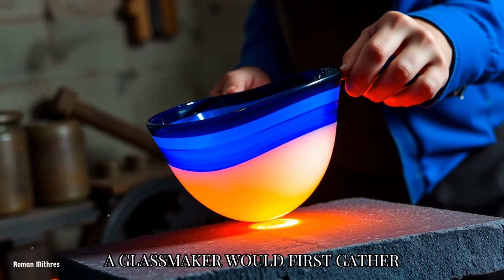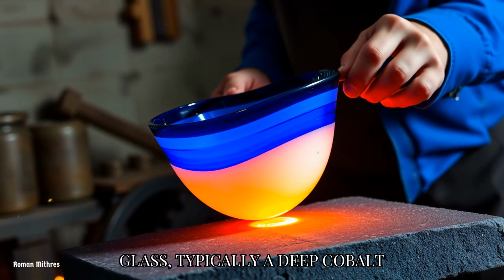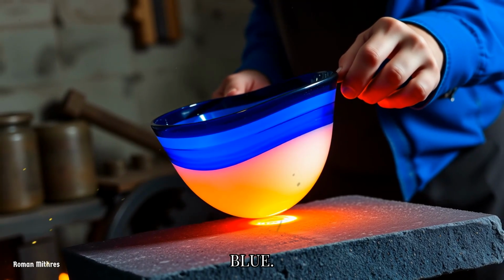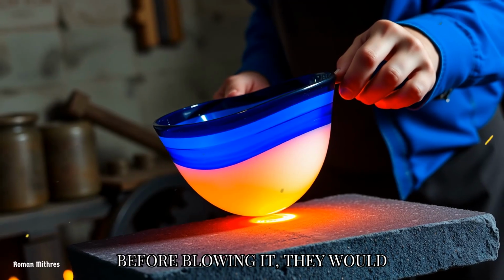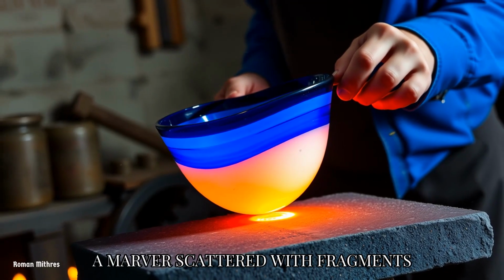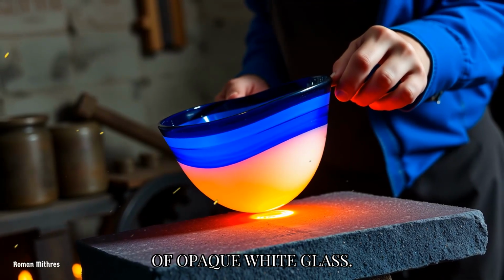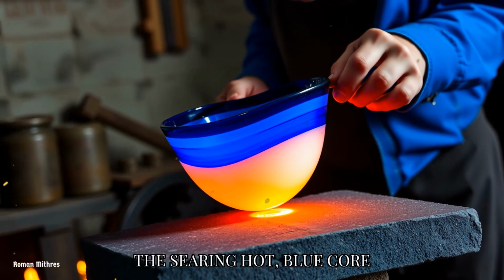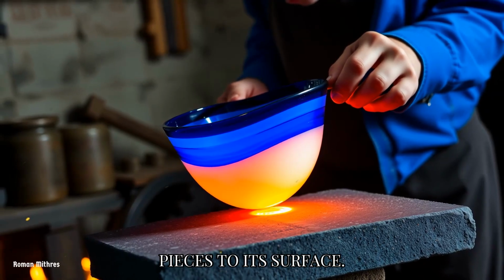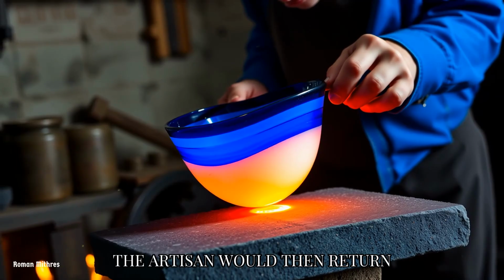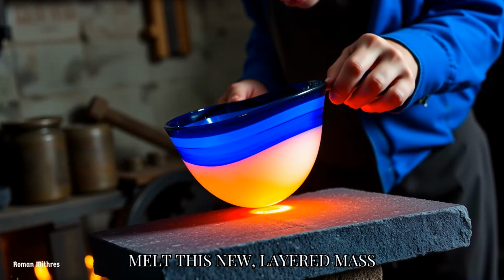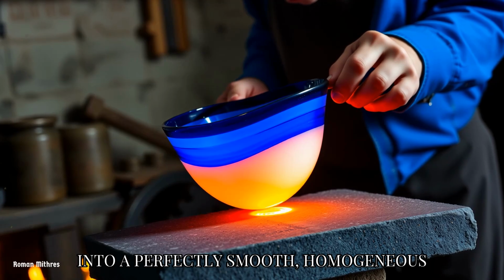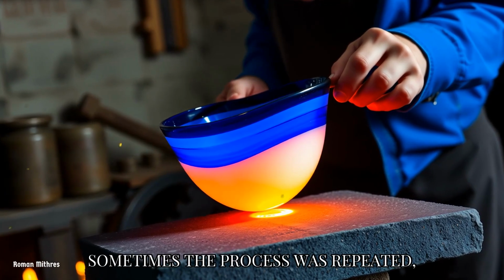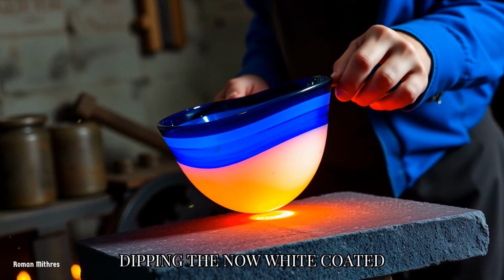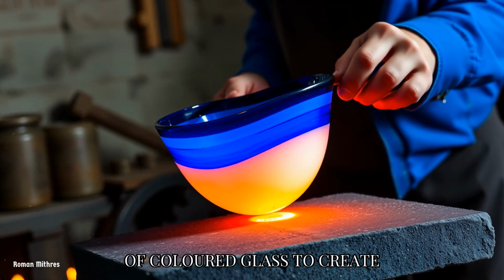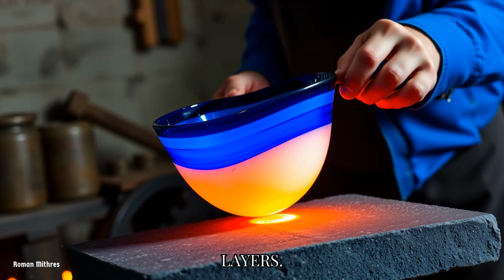A glassmaker would first gather a parison of intensely colored glass, typically a deep cobalt blue. Before blowing it, they would roll this glowing gather over a marver scattered with fragments of opaque white glass. The searing hot blue core would instantly fuse these white pieces to its surface. The artisan would then return to the glory hole to melt this new, layered mass into a perfectly smooth, homogeneous bubble. Sometimes the process was repeated, dipping the now white-coated gather into yet another pot of colored glass to create three or even more distinct layers.